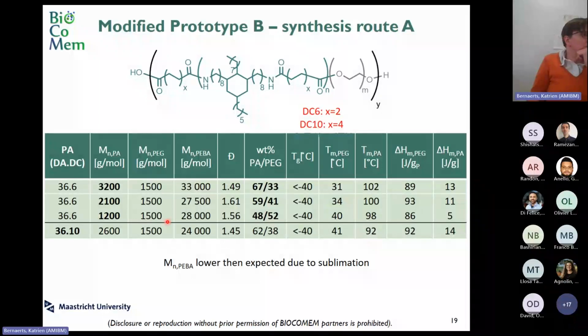So if we look to the results, the first set of results, there are 3 experiments where we combine the fatty diamine with sebacic acid, and we varied the molecular weight of the polyamide between 1,200 and 3,200, which results in a different weight ratio of polyamide to PEG in the PEBA. We also see that all the polymers have a polyamide melting point and a PEG melting point, where the polyamide melting point is around 100 degrees. That is a good range.